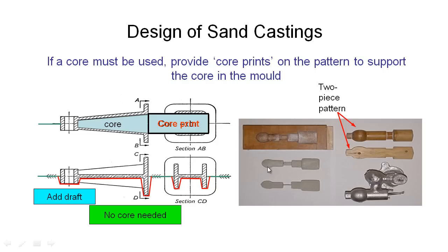So this is a core that would come out of this mold once we've baked the sand in the oven. This is nice and rigid, and it's even got an additional bit of wire going through there to give it some extra support. And down the end of the component here, we have our core print. This is not actually the part at all. You can see that this doesn't come out in the final part, but it's going to be completely filled by the sand in our core. So that's how you can tell what's a core print.